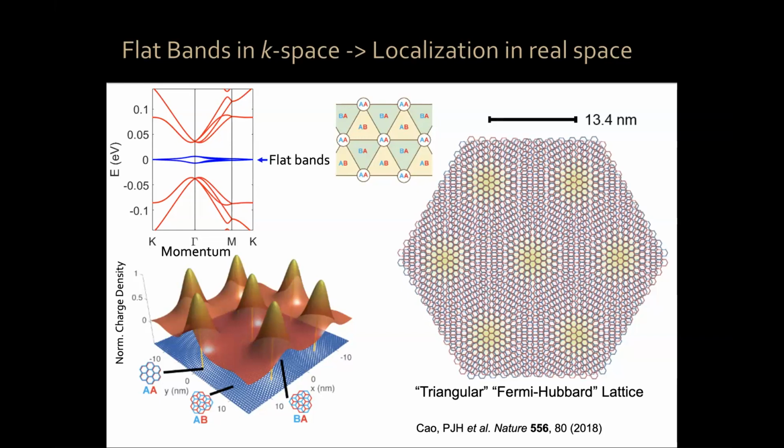You don't have these very flat bands. Okay, the band. There is a continuity. I have a video which I could have shown with the evolution of the electronic structure as a function of twist angle. You go from Dirac cones, and then maybe around 2.5 degrees or so, these Dirac cones start to experience a serious renormalization of the velocity. But then it becomes dramatic in the vicinity of 1.1. From 1.3 to 1.1 is a dramatic flattening, and then below 1 again it changes. You go out of the flat band condition, so to speak. So all the magic, as I will show, happens roughly between 1 and 1.2 degrees.